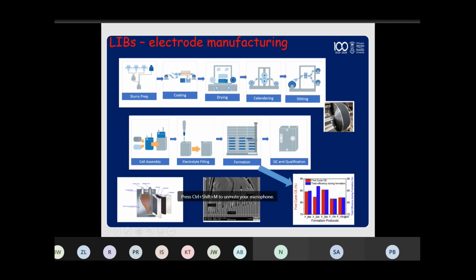This is because, of course, if it's too thick, you will have problems of lithium diffusing throughout. You can have problems of mechanical stability. This is a huge problem because, as I said, the lithium diffuses in and out of the electrode, therefore it expands and contracts constantly. This creates stress within the electrodes and ultimately delamination. So the thickness is another important parameter that has to be optimized during the coating process.